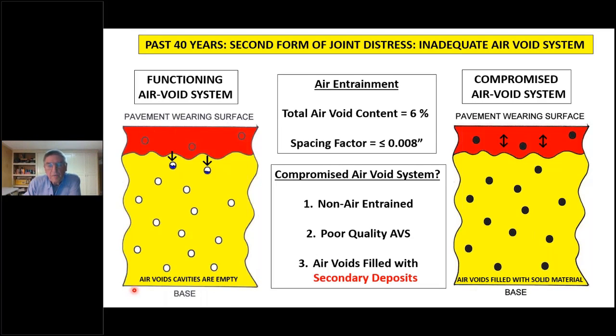So this form of distress that I'm talking about now, I called D-cracking, was associated with water getting in, freezing and thawing. What is going on today is a compromising of the air void system. In a functioning air void system, over there on the left, in front of the advancing ice front, the water gets pushed into our little open rooms, which are the air void cavities, and is allowed to freeze in there, so that when the expansion from water to ice takes place, it's accommodated. In situations where the air voids get filled with secondary deposits, they no longer can perform their intended function, and we're pretty much back to non-air entrained concrete. So I'm calling it a compromised air void system.